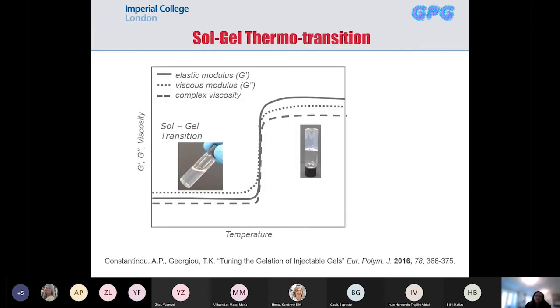Now, for all of these applications to be utilized, what is important is the gel point, so the temperature where we have the formation of the gel. Rheologically, it is, of course, where the viscosity will increase and where the elastic modulus will exceed the viscous modulus. So at this point here, for example, we have the formation of the gel, and you can visually observe it by a very simple test. You just invert the tube. If this doesn't flow, we consider it a gel. And normally the rheological curves and the rheological gel point do match what we see visually, within a couple of degrees. So tuning this gelation point is crucial because it's important to know where we're going to get the gel. And of course the temperature, depending on the application, is important.